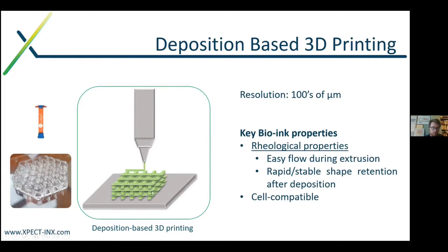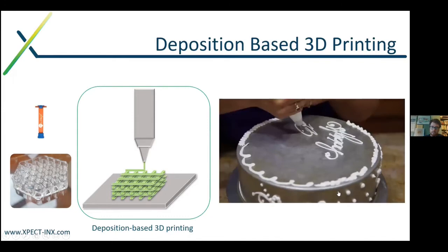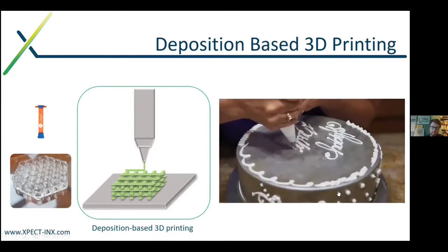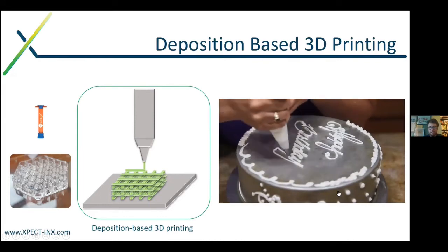Now, there's a lot of research here, and what is the key feature of bioinks in this segment are the rheological or the flow or viscosity profile of the material. So what you preferably want is a material which has an easy flow during extrusion, so that it's very liquid to exit the nozzle. But once it has left the nozzle, you of course want it to maintain the structure which you've created, so to have shape retention, and of course they also need to be cell-compatible. So what you're basically looking for is a material which behaves like icing on the cake. You can easily extrude it and it maintains its shape.